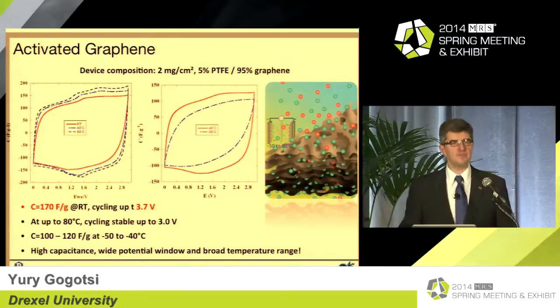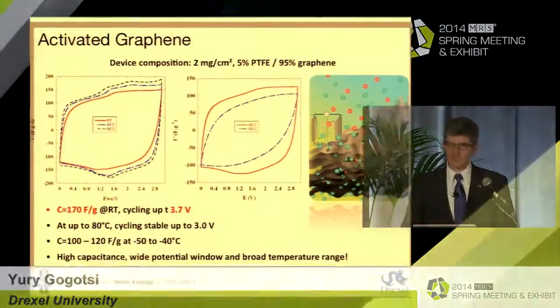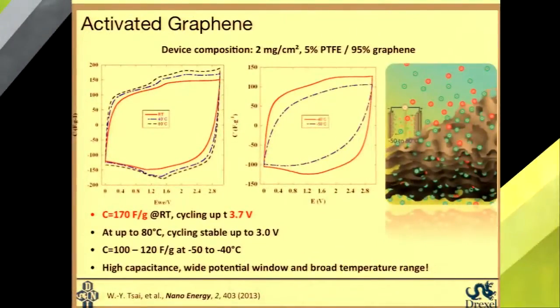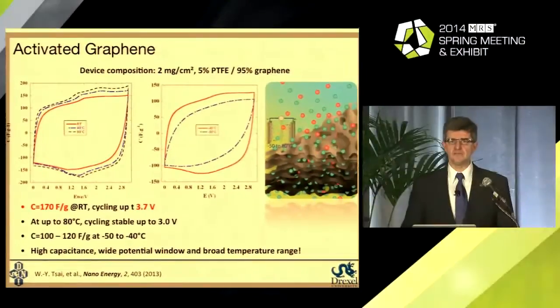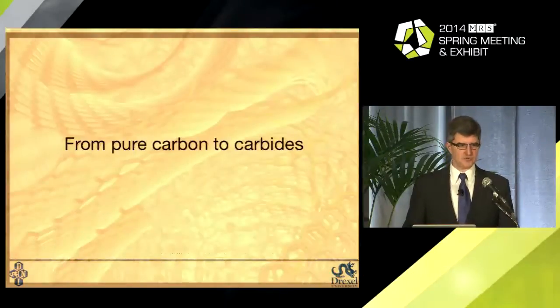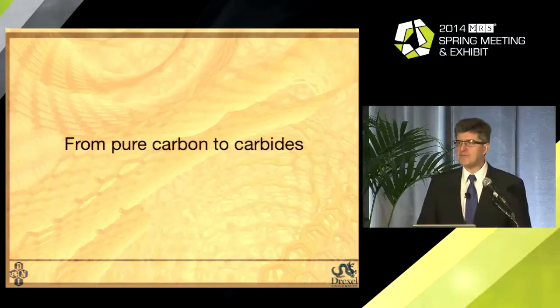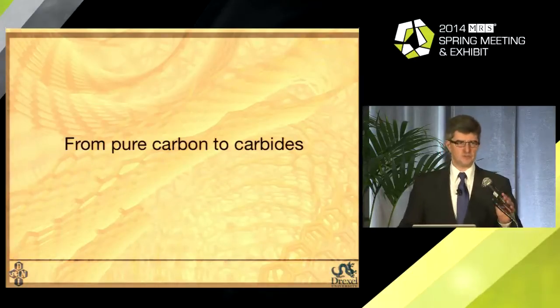Since, as you may remember from the equation I showed you, energy is proportional to capacitor voltage squared, it pretty much right away doubles the energy of the device. Moreover, we can still go to high temperatures and we can get a very good capacitance level of current devices at -50 degrees C. So again, by designing this carbon, we can improve performance, improve capacitance, and at the same time keep the temperature range. So there are many, many different opportunities here.